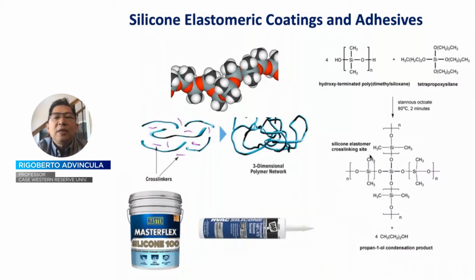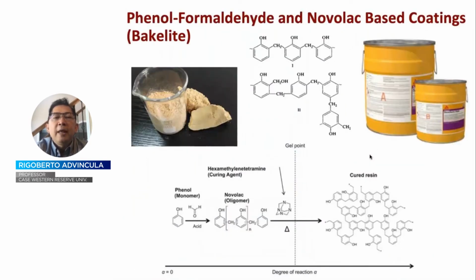Silicone elastomeric coatings and adhesives are very well known for durability, for non-wetting, and for the ability to have good chemical resistance. The type of coatings based on silicone are typically elastomeric, meaning you can rely on them at, for example, sub-zero service temperatures. Phenol formaldehyde and novolac-based resins, probably together with epoxy, constitute some of the more cost-effective methods as well. And this is very old chemistry. In fact, if you've heard of the term Bakelite, this is basically phenol formaldehyde chemistry that results in very durable thermoset materials or conditions for coating.